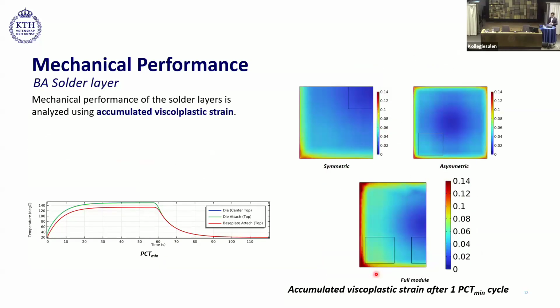Now I will go through the mechanical performance of the base plate attached solder layer. Again, here we use accumulated viscoplastic strain as a performance criteria. And this was done during PCT-min power cycling. So in the symmetric and the asymmetric case, we observed that it's mostly the corner regions which exhibit higher viscoplastic strain accumulation. We didn't see much difference between symmetric and the asymmetric case, but in the full module, we see that a big portion of the edge experienced higher viscoplastic strain accumulation.